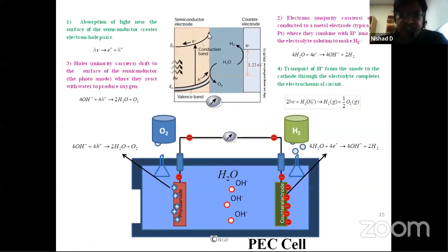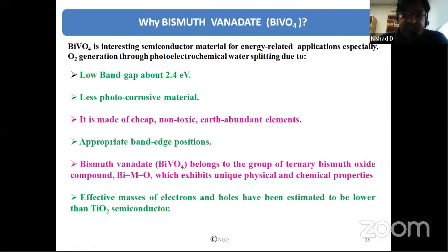What we are utilizing here is bismuth vanadate. We are trying to understand bismuth vanadate because it has a low band gap, almost 2.4 electron volts. It is a really less photocorrosive material. For studying the commercialization aspects, you need a material which withstands for a longer time without any deterioration in its properties. This is a very important aspect of bismuth vanadate. Not only that, it is cheap, non-toxic, and abundantly available. So making bismuth vanadate is quite easy, and for commercial purposes also very economical. It has very perfect band edge positions for splitting water to produce H2 as well as oxygen. So it is a very important material.